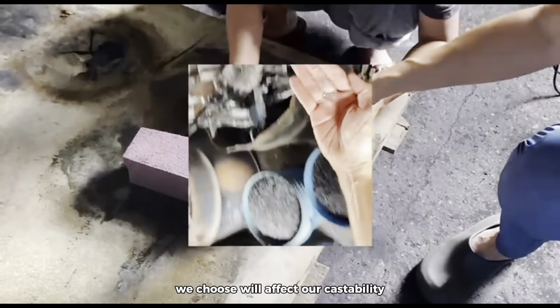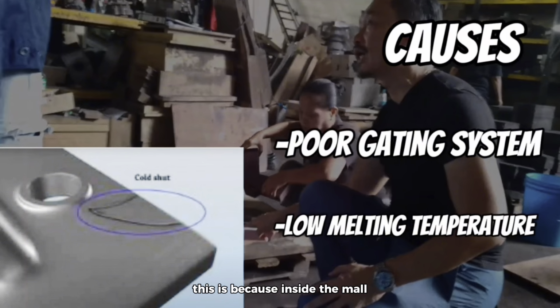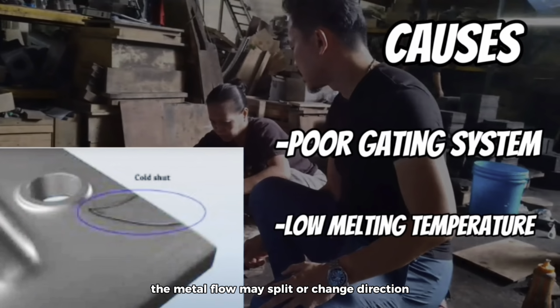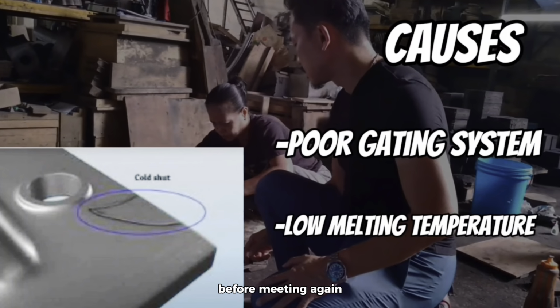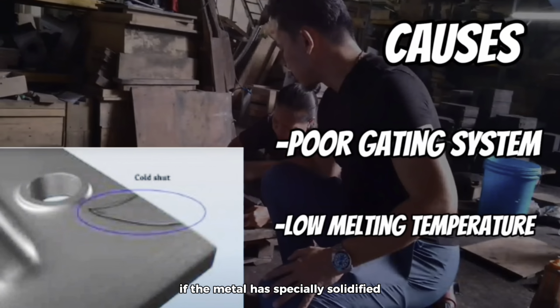Another problem faced is cold shut. This defect occurs when two streams of molten metal meet but fail to fuse properly, usually because the metal has already begun to cool before they join. Even if there is only a single main stream poured through one gate, cold shut can still happen. This is because inside the mold, the metal flow may split or change direction before meeting again. If the metal has partially solidified when the streams reunite, they won't bond well, resulting in a visible line or crack known as a cold shut.